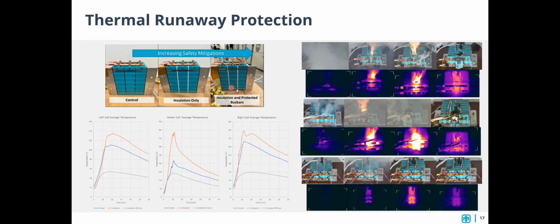So what happens when we short the center cell in our control is we see it goes into thermal runaway, and that heat will spread to the 2 adjacent cells, heating those as well and causing those to go into thermal runaway. If we just have insulation and cause the same kind of thermal runaway in the center cell, we see that insulation actually doesn't prevent the heating of our 2 adjacent cells, because as soon as the center cell is shorted, that essentially, because these terminals are connected, creates a short in these other 2 cells as well.